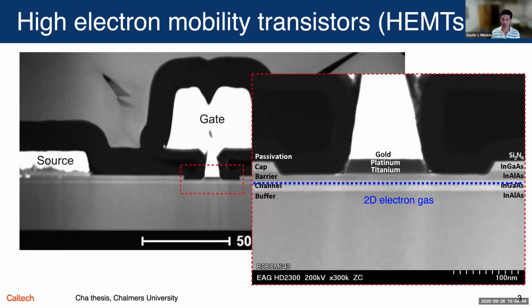The reason that these particular HEMTs are so important for low noise application lies in this heterostructure that you see on the right. The origin of the name high electron mobility comes because the conducting channel hosts a 2D electron gas. The dopants are actually located in the barrier just adjacent to the channel. As a result, even when you cool this device, the electrons in the gas remain highly conductive. And in fact, they become more conductive at low temperatures. And that allows you to get this fantastic high frequency and low noise performance down to 4 Kelvin.